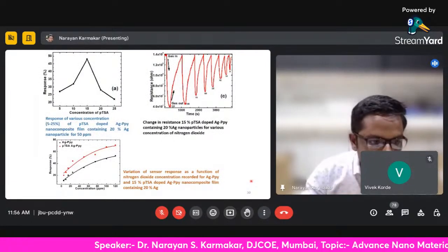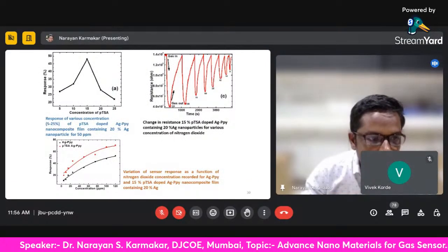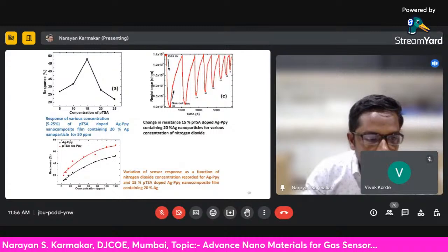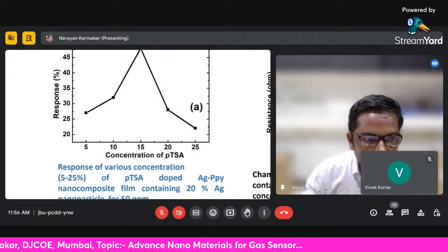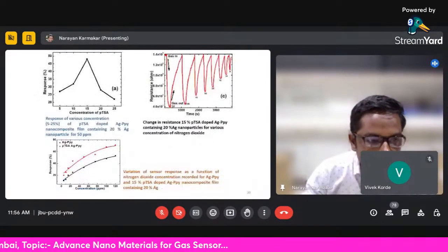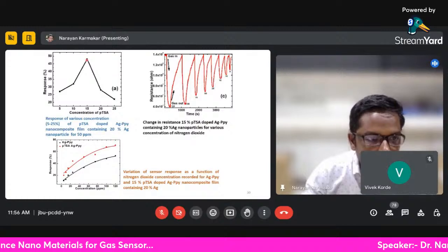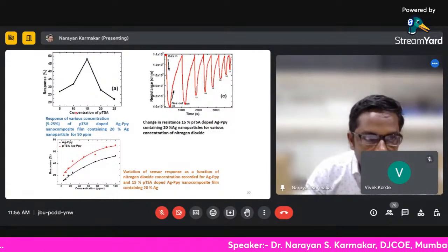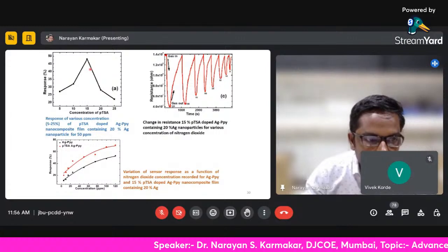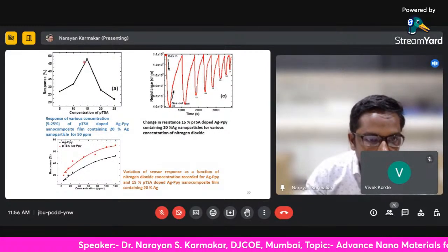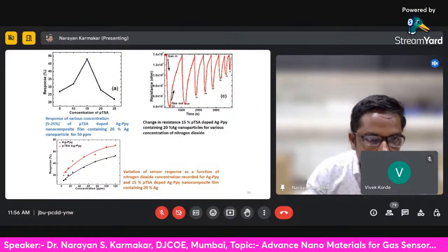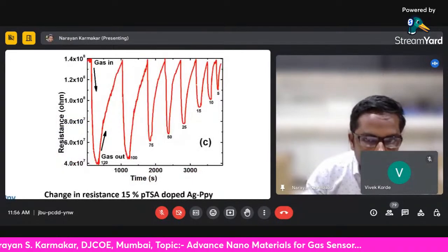Now look at these readings. When doped with PTSA, the response of this gas for 50 ppm, the maximum response we got was about 15%, at 15% doping. We got a maximum response, and again we studied the variation for different ppm of the gases, where the overall response increases.